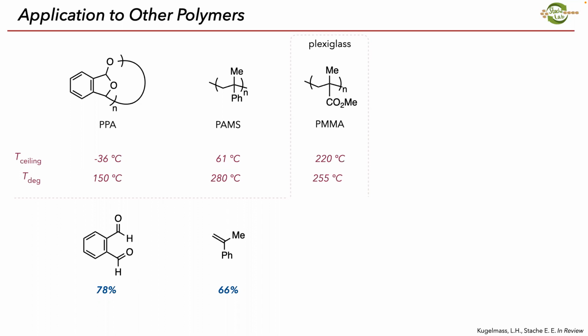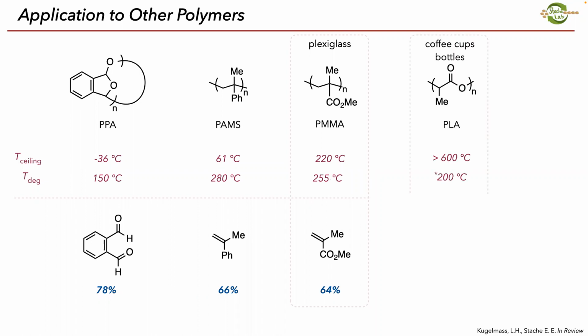Moving on to commercial polymers, so plexiglass, PMMA. The kinetic barrier, so the degradation temperature, is similar to that of poly-alpha-methylstyrene, but now the thermodynamics are really working against us. 220 degrees C to drive that process in reverse. And so in this case, we needed to actively pull off monomers. We did this under vacuum, but we can still get the polymer to depolymerize back to monomer in 64% yield.